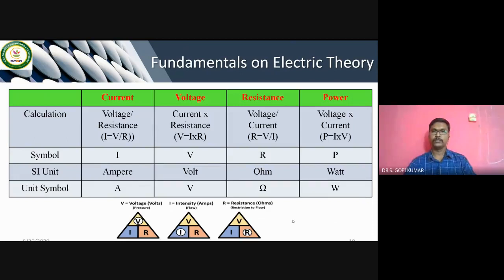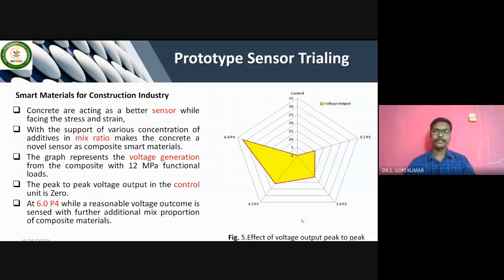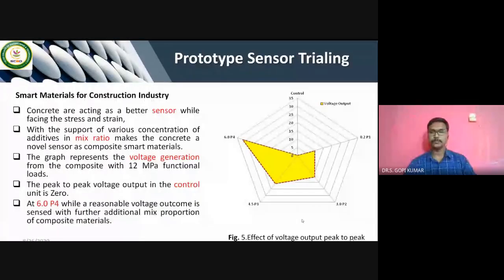Now, prototype sensor trialing. In this case, the voltage output is monitored, where the graph shows the effect of voltage output peak to peak ranging from different compositions, where in control the voltage is nil, where for 0.2 percentage, 3.0, 4.5 and 6, it shows higher voltage power flow for the largest amount of carbon nanotube and cement composition, where this experimentation is carried out with external load of 12 MPa.